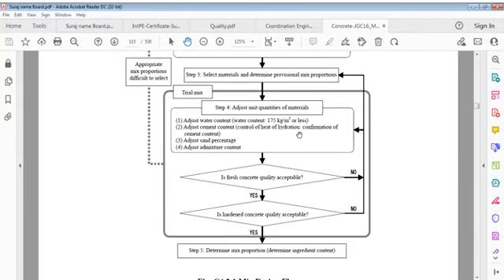Step 4, adjust unit quantities of materials. Adjust water content. Water content will be 175 kg per cubic meter or less. Adjust cement content. Control of heat of hydration. Confirmation of cement content. Adjust sand percentage. Adjust admixture content. This is here.